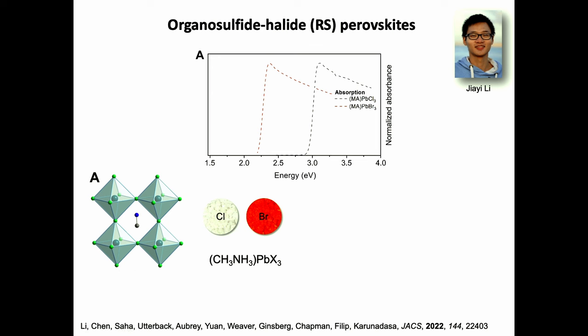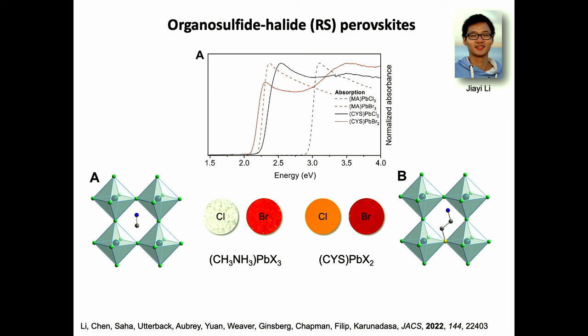But if you look at the consequences of adding sulfur to this material, what you now see is that these band gaps become very similar. It's almost as if the perovskite band gap no longer cares whether there's a chloride or a bromide, as long as you stick a sulfur into this framework. And remember, I only replaced one of the halides out of 3 with sulfur. So why is this?